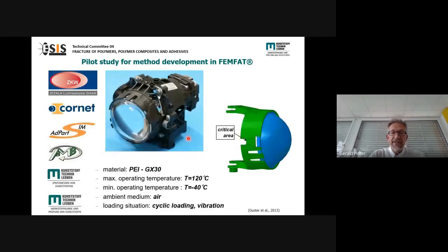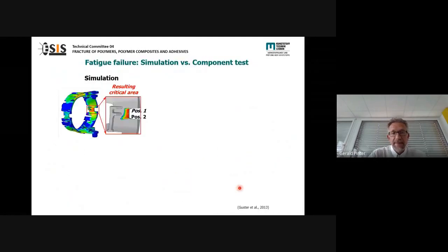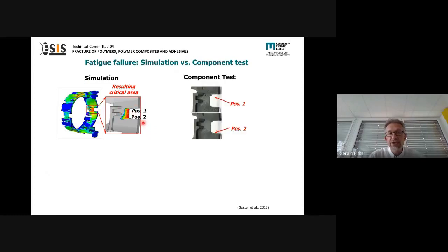And here, for example, I also want to show you that we use this already for quite complex components. This is a so-called lens holder, and the material is PEI, 30% glass fiber reinforced. Based on all the calculations after the experimental evaluation of our results, we get a fatigue simulation of the most critical areas. We found these two positions. Also, we did component tests, and we got a really good correlation between simulation and component tests.